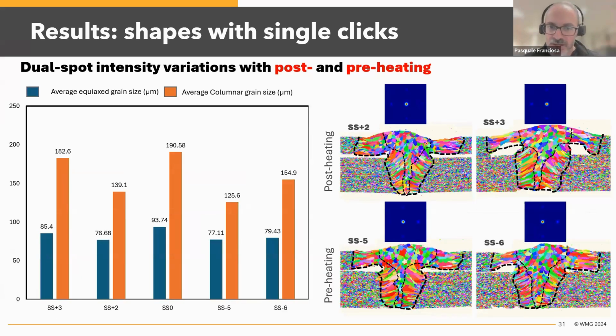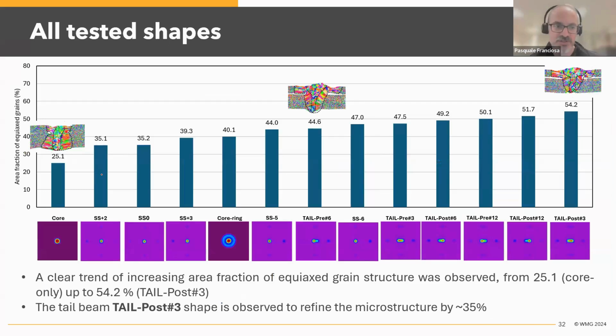Now, if we go to the analysis of the grain structure, on the slide you see some of the EBSD maps, which are probably the most relevant ones. You can see from the bar chart the distribution of equiaxed grain and columnar grain. There is a trend, but more interesting is to see the full picture. This is plotting the area fraction of equiaxed grain, starting from the core-only static beam distribution, to the tailed beam profile with a slightly higher peak intensity towards the front of this elliptical distribution. And you can see how the bar chart looks.